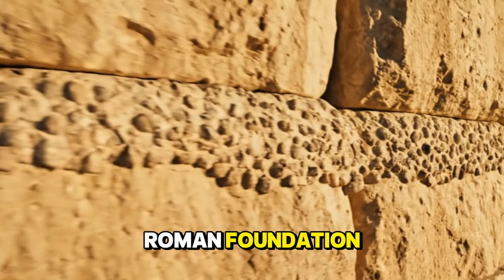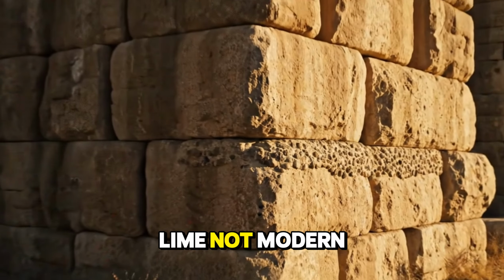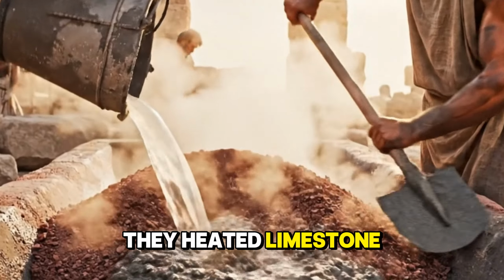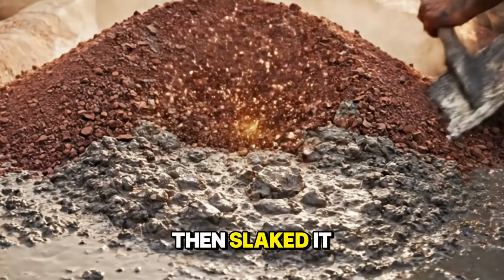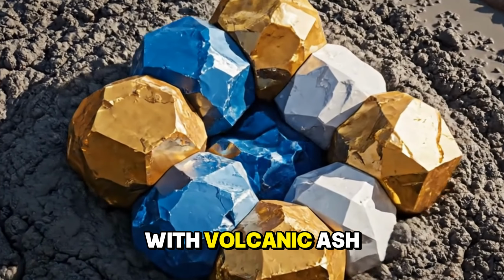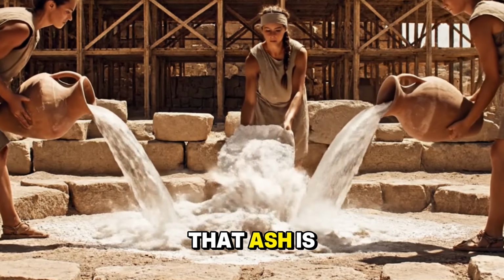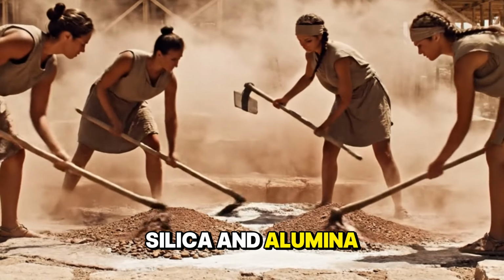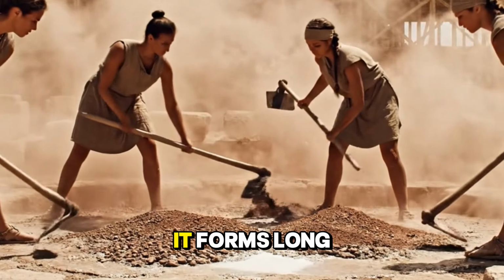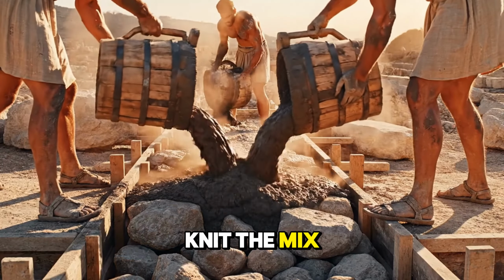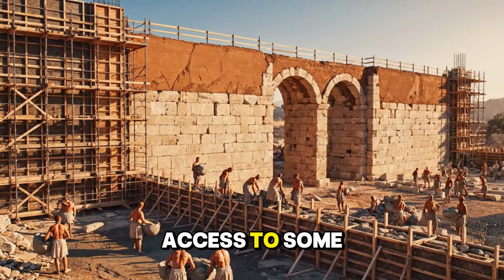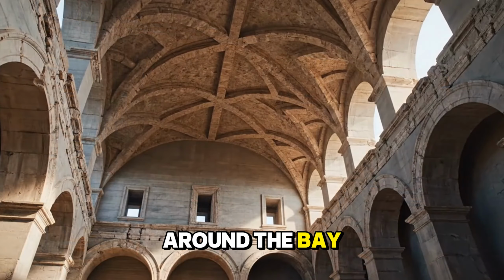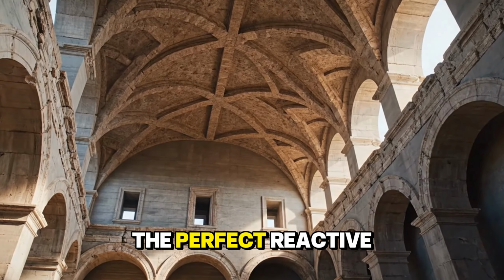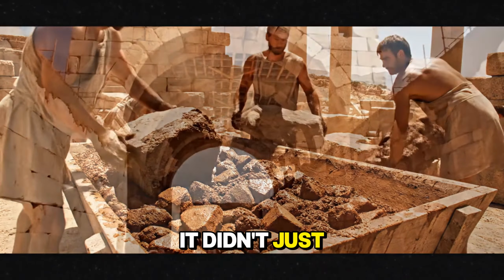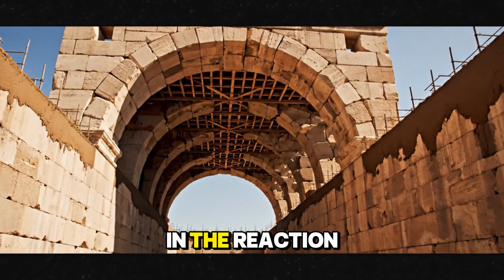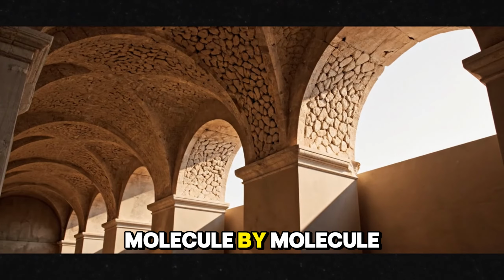Here is the Roman foundation. Their binder was lime, not modern Portland cement. They heated limestone to make quicklime, then slaked it with water, then blended it with volcanic ash known as pozzolana. That ash is rich in reactive silica and alumina. When it meets lime and water, it forms long-lived minerals that knit the mix into stone. The Romans had access to some of the best ash on Earth around the Bay of Naples. Think of it as the perfect reactive filler. It didn't just bulk out the mix. It took part in the reaction and built durability molecule by molecule.